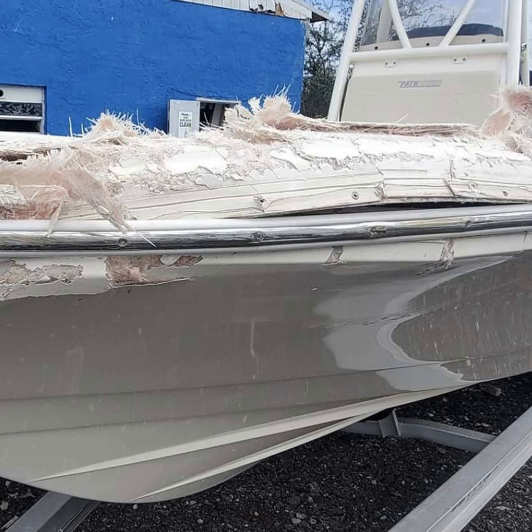You're going to remove the gel coat until you can see the fiberglass, and then you're going to assess the damage just visually. You can pour some acetone, I've said a few times already. You can pour some water on it because you're going to grind it. It's going to dry, whatever. I mean, use your common sense. Don't get your masking all wet. But you can do something so that you can start to get the dust off the surface of the fiberglass and wet it temporarily so you can look into it instead of just on the surface of it. And you just want to grind until you get rid of anything that's damaged.